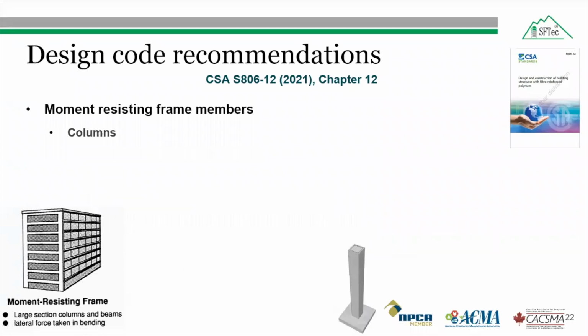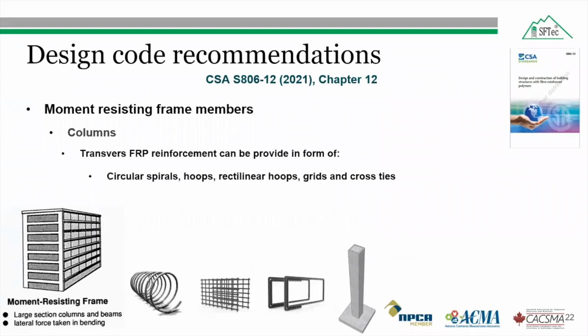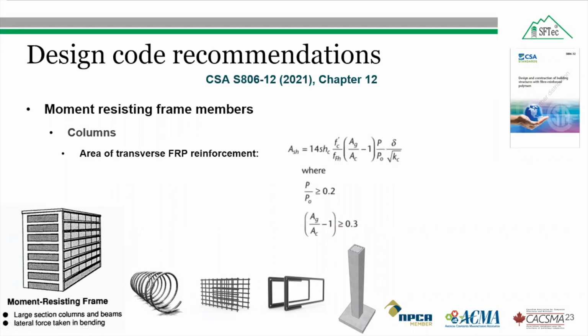So the column member of the moment resisting frame should satisfy the relevant seismic provisions of the CSA A23.3 with longitudinal steel reinforcement, and the transverse fiber reinforced polymer reinforcement should be provided in the form of either circular spirals, hoops, rectilinear hoops, overlapping hoops, grids, or cross ties, which is shown in the figure below. The required area of the transverse FRP reinforcement should be calculated using the equation as shown here. And here P by P naught is the axial load ratio, which should be greater than or equal to 0.2, and Ag by Ac minus 1 should be greater than or equal to 0.3.